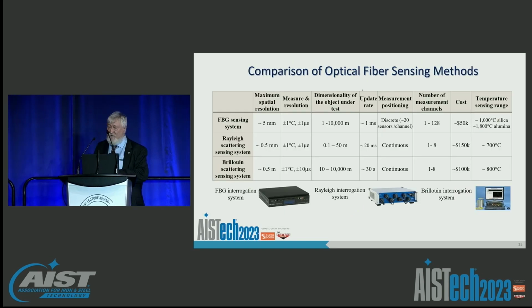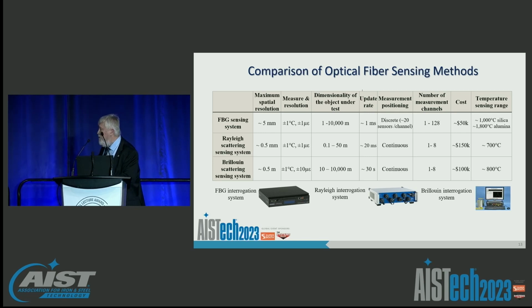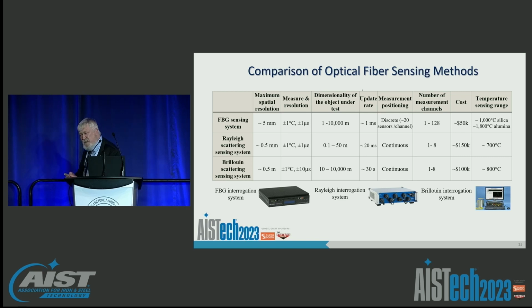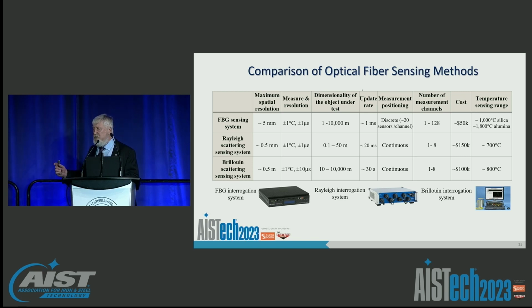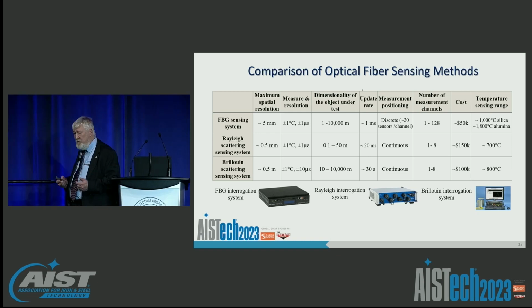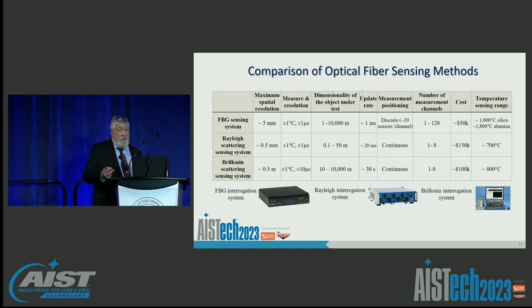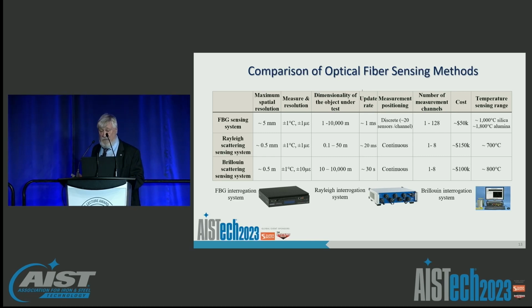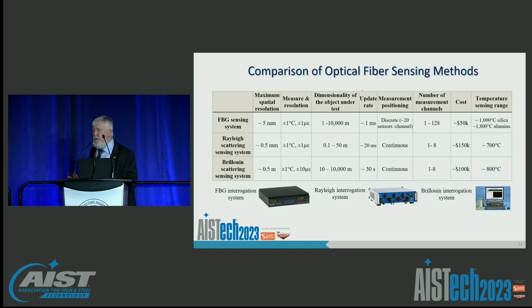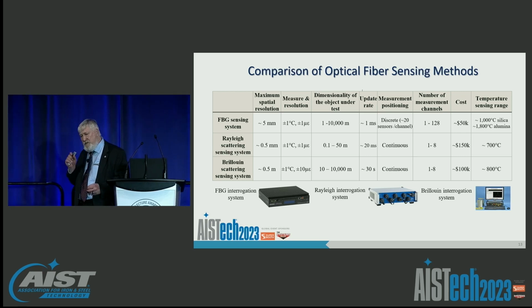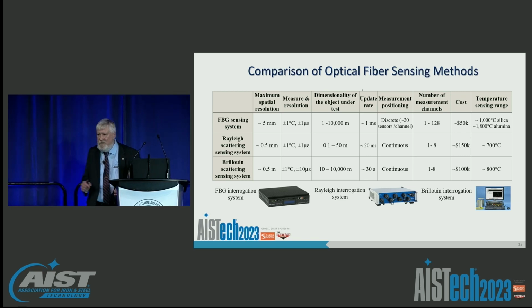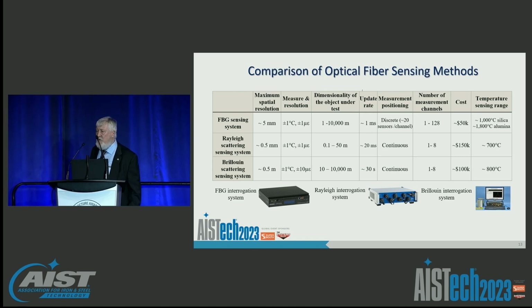So there are a number of different methods that I've already highlighted. And I just wanted to summarize some of them here, because each has its own distinct advantages and disadvantages. If I look at fiber Bragg gratings, typically the maximum spatial resolution you can get out of those fiber systems with Bragg gratings etched on them is about 5 millimeters, which is great for a lot of applications and actually being used in continuous casting molds today. They can sense, though, at very long distances, up to 10 kilometers in length. But their one restriction is that typically you're limited to the number of sensors you can put on the fiber, because each one has to have a distinct frequency. And so typically we can have maybe up to 128.